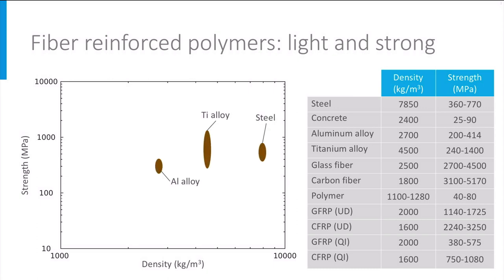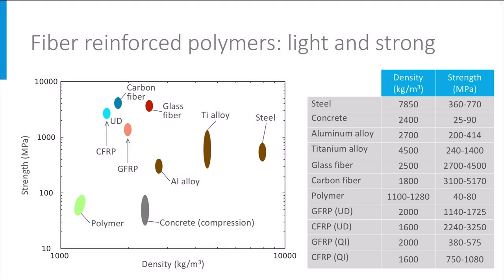If we remake this chart for strength, the relative location of the metals is similar, with a strength of 360 to 770 MPa for steel and 200 to 414 MPa for aluminum. The strength of concrete, even the compressive strength which may go up to 90 MPa, is significantly lower than that of the metals. The polymer matrices that we use have a strength in the range of 40 to 80 MPa — accounting for the low weight, that is already good. The fibers are performing really well when it comes to strength; both glass and carbon have a much higher strength than the classical engineering materials, at 2700 to 5000 MPa. When combining fibers and polymer, the strength that can be reached in UD-FRP is still higher than that of steel, at 1000 to 3000 MPa.